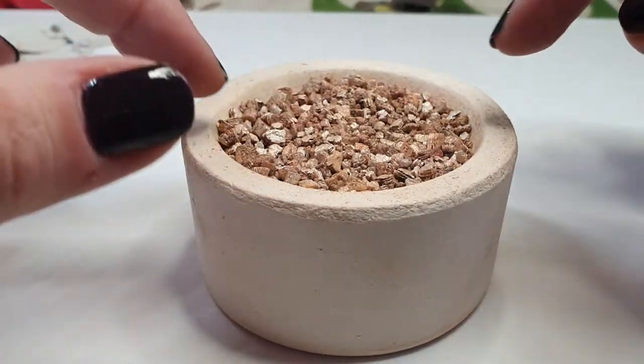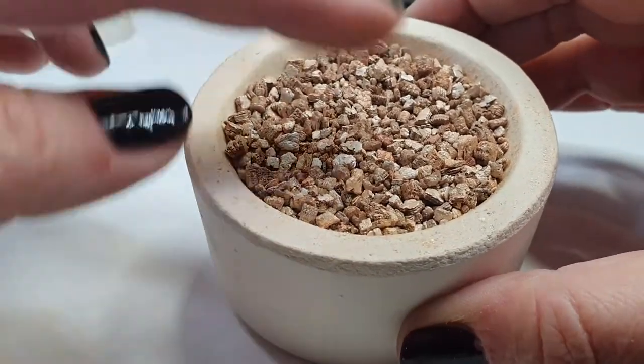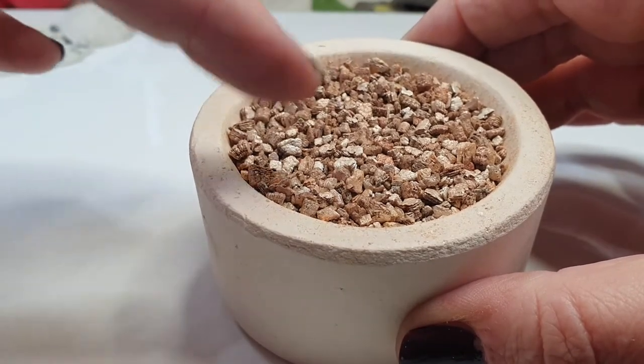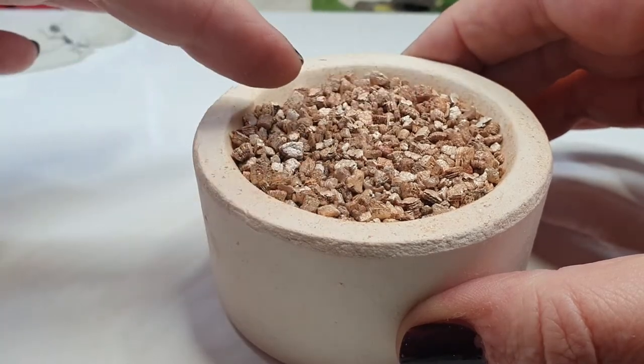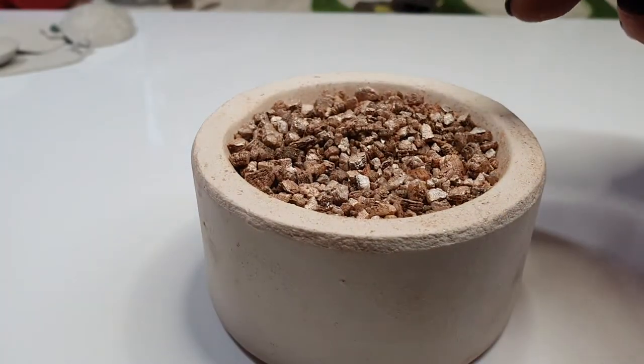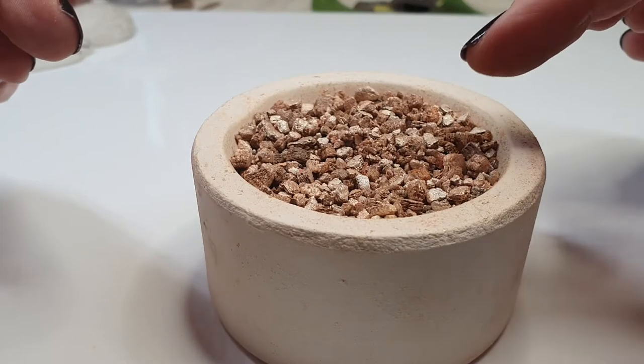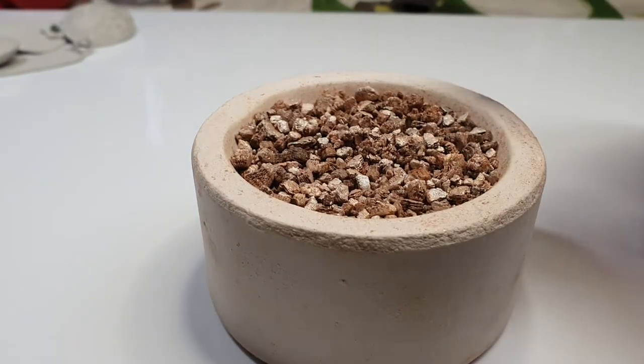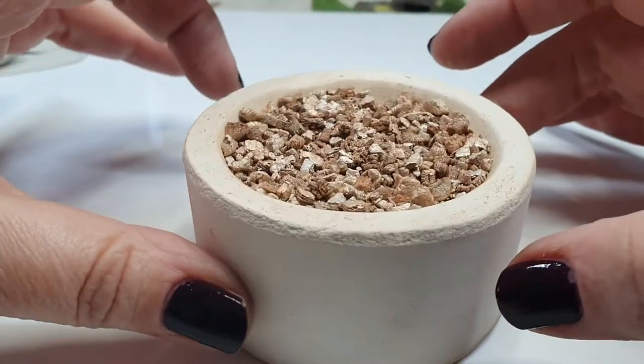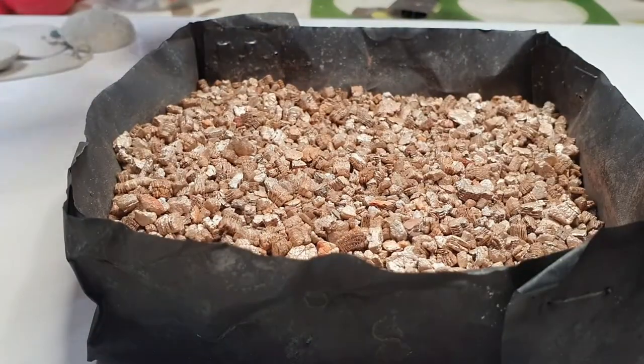This is a very fine vermiculite. If you're choosing to buy vermiculite, you can get it cheaper from garden centers than from some metal clay outlets, but you have to make sure it's this size because the ones from garden centers are much bigger. You can take a knife, chop it up — it's quite soft — and make it finer. The reason you'd want it finer is that vermiculite can cause pitting on the surface of your silver, so you want it as small as possible.